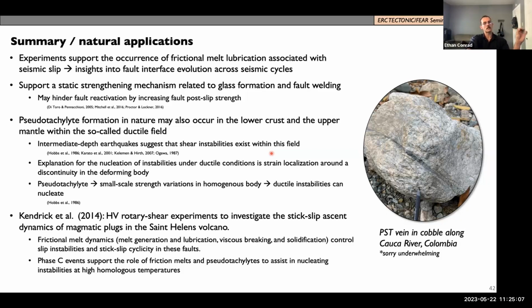And then Kendrick 2014, also in a very hot setting, the Mount St. Helens volcano, used high velocity rotary shear to investigate the ascent of magmatic plugs. They used acoustic emission sensors, and people have described this kind of drumbeat of acoustic emissions, suggesting that the ascent is stick slip along these faults bounding the plug. And our phase C events support the idea that frictional melts and pseudotachylites assist in nucleating those instabilities and also in arresting the slip of those instabilities at these higher homologous temperatures.